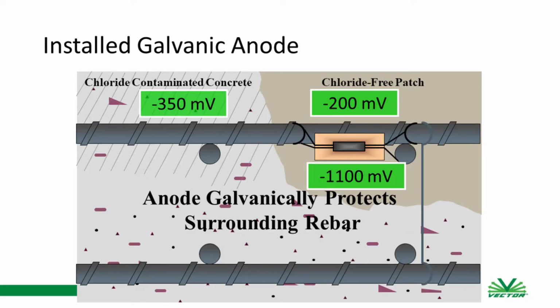So by tying on these galvanic anodes, they're zinc cores with a high pH mortar around them to keep the zinc active, and then that'll help not only protect your reinforcing steel within your patch, but all that surrounding contaminated concrete that's more electronegative. So that's going to help stop or prevent that ring or that halo effect that you may have seen in some of your repairs.